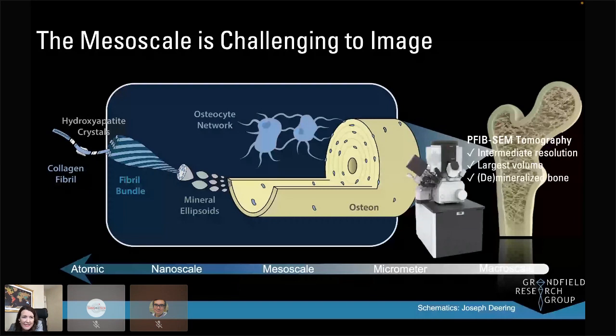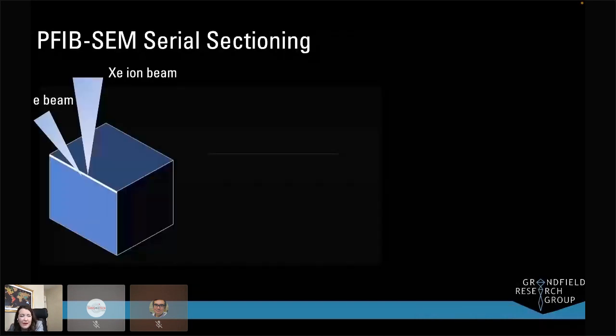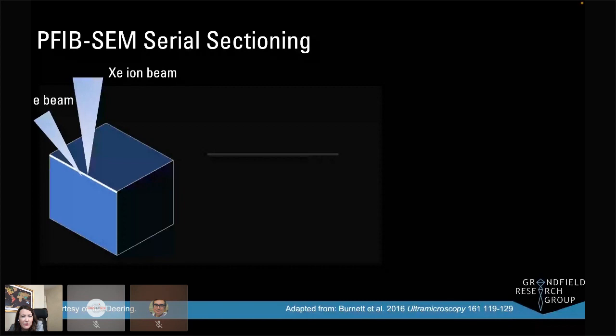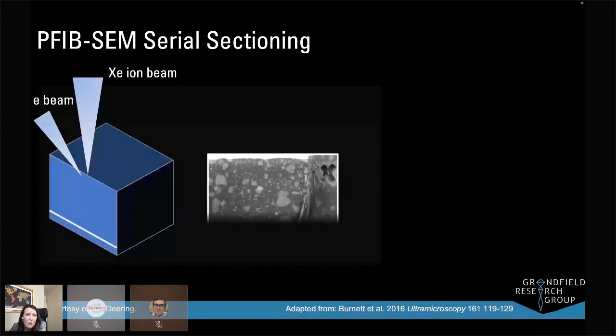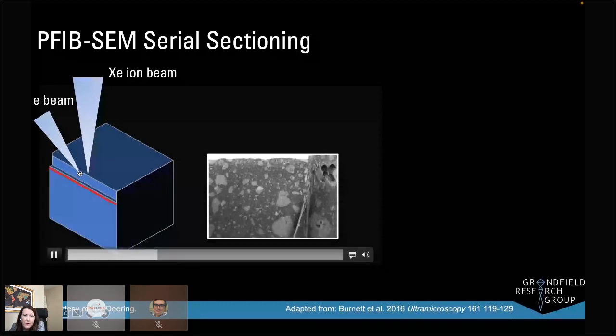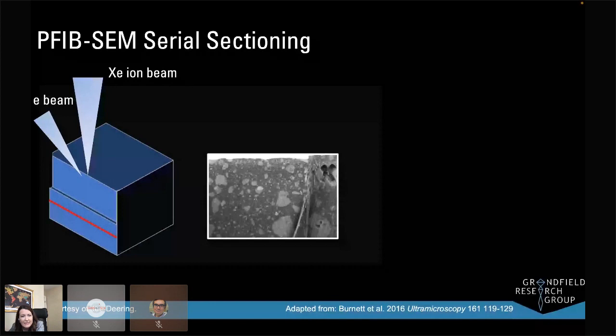So what is this plasma FIB tomography technique, or serial sectioning? Well, like the focused ion beam I showed earlier to prepare TEM samples, we have an electron beam, but we also have an ion beam—in this case xenon—which mills material much faster than gallium. So what we do is use this ion beam to mill away a slice of material. You can think of it like slicing a piece of bread, and we cut away a surface of the bread, and then we take an image.